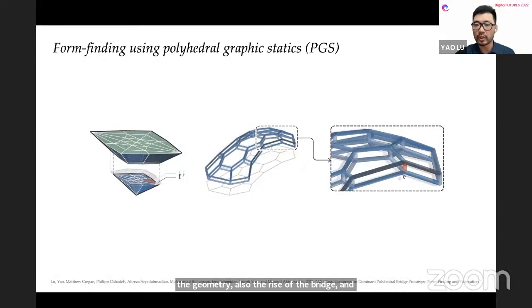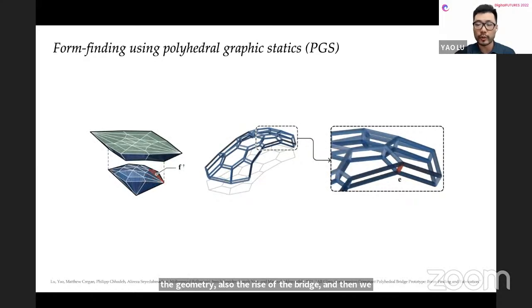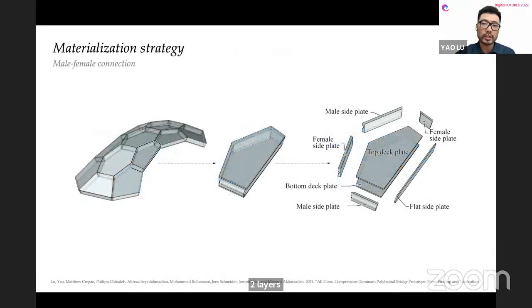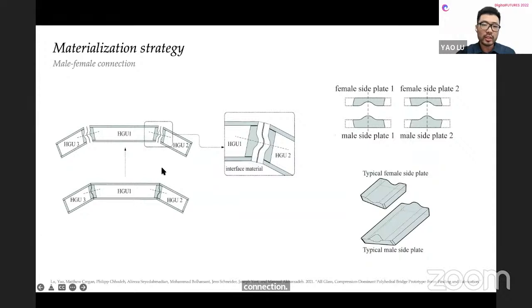And then we quickly move to the double layer bridge just by simply subdividing the force diagram into 2 layers. And after getting this base geometry, each of the polyhedral cells will be materialized into one hollow glass unit, which has a top deck plate, a bottom deck plate, and several side plates. We were trying to use the 1 centimeter annealed glass as much as possible, but for some of the side plates, we have to make them thicker in order to accommodate some connection mechanisms called the male and female connection mechanism. So this mechanism is mainly to try to avoid the relative sliding between the neighboring hollow glass units.